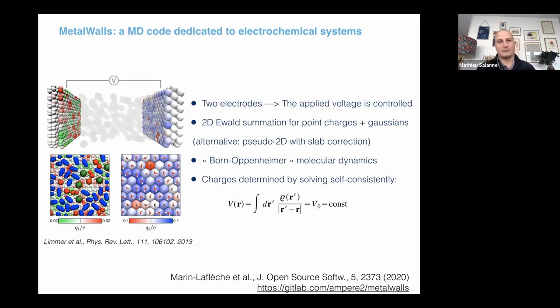Due to the geometry of the system, we use 2D Ewald summation for everything. So for point charges, Gaussian charges, and even dipoles, because we can have some induced dipoles in the system. And instead of using Car-Parrinello type molecular dynamics, we do Born-Oppenheimer, which means that we have to calculate the charge at each step. So at the beginning, this was made using conjugate gradients mostly, but in fact, in most cases, we have rigid electrodes, so they don't move, and it's even simpler to do it by computing the matrix, inverting it, and solving at each step using this approach.